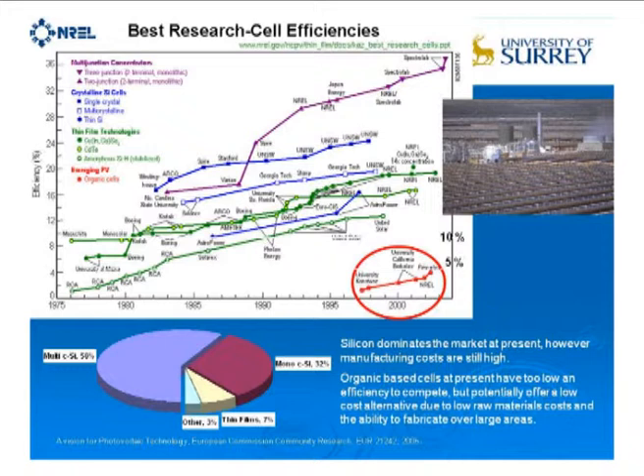It's expensive because you generally tend to use crystalline silicon materials that are hugely expensive to produce, and you are looking at thick materials when it comes to crystalline materials in order to absorb things. If you take a crystalline silicon solar cell, you're effectively talking about 200-300 microns of material that has to be used in order to absorb things.